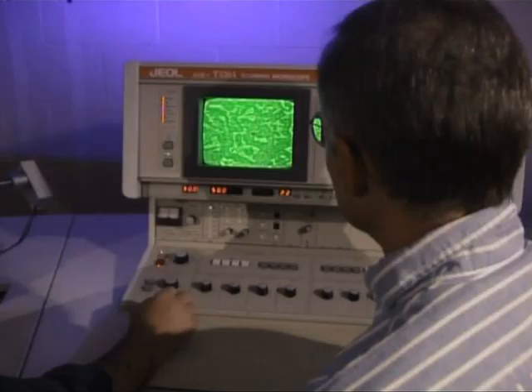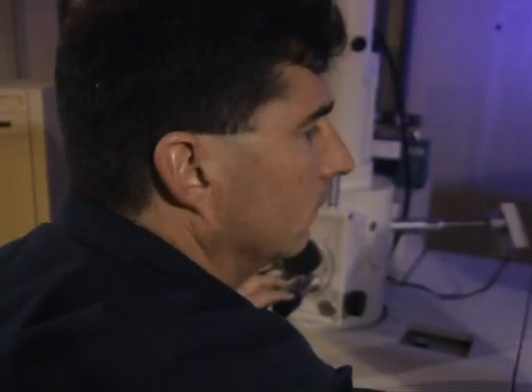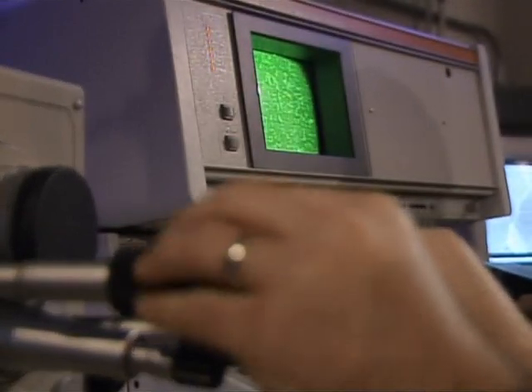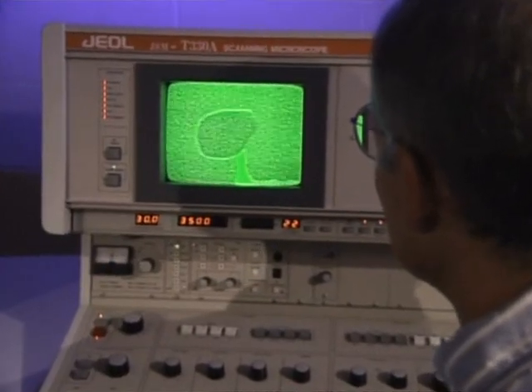Metallurgists Chris Ramsey and Scott Miller peer deep into the steel's microstructure. Pearlite, lots of inclusions. Let's focus it real fast, and then go back down in magnification, see what we have. They are looking for potential weaknesses and defects in the steel. Higher magnification shot. Lots of ferrite, pearlite, big inclusion. That's a big one. Probably big old manganese sulfide. That's a big one. Big manganese sulfide.